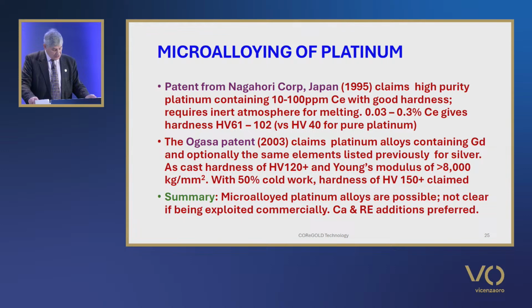The Ogasa patent, that I mentioned earlier, also includes platinum materials, and this claims platinum alloys of at least 85% platinum containing gadolinium and the other optional elements listed above for silver, preferably calcium, in the range 50 to 15,000 parts per million in total. Cast hardness values of at least 120 Vickers and Young's modulus of not less than 8,000 kilograms per square millimetre are claimed. With 50% cold work, hardnesses of at least 150 are claimed. Thus, in summary, it is evident that microalloyed platinum alloys are possible, although it is not clear whether they're being commercially produced, and that the rare earths and calcium are preferred microalloying additions, paralleling that of the work on gold.